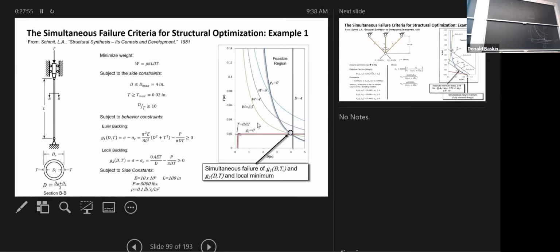The way they do this is very clever. They equate the formula, the stress for local buckling, to subtracting the stress at the part and the critical stress for the material. And therefore, if that function goes to 0, then you have a no-go. You've broken the constraint. Local buckling is that tiny red line on the side? Yeah, it's this tiny red line that goes like this. Does it follow along with the T2? Probably not exactly, but pretty close.